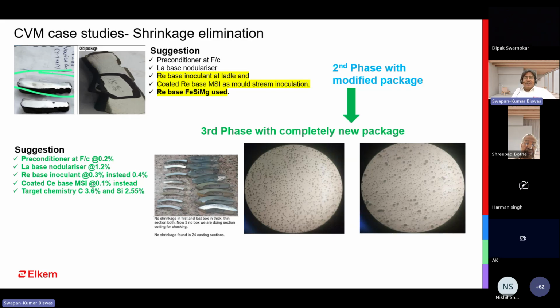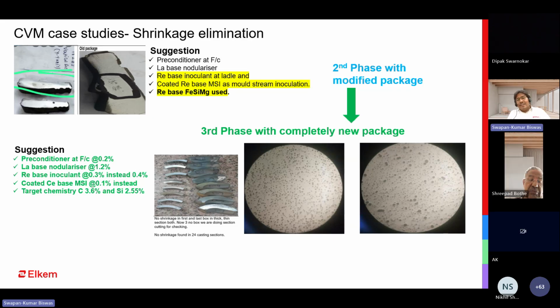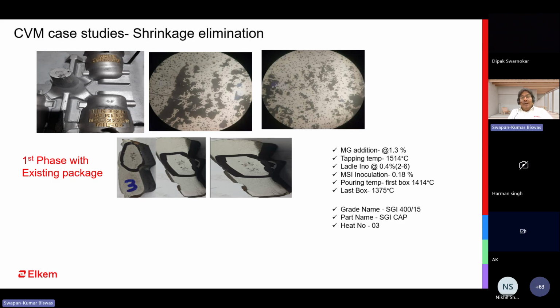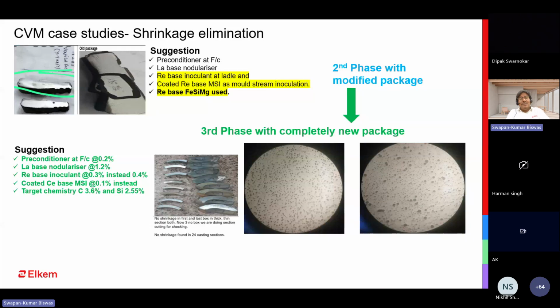So then inform the customer to try this complete combination, because your structure is not good enough, even though you have partly used the suggested combination and partly decided yourself. In the last stage, you can see a huge change in the microstructure, especially nodule size and distribution of nodules. When we started, this was the structure, and at the last stage, when our activity was completed, this is the structure. That is the change: the same metal, same chemistry, but a huge improvement in the microstructure.